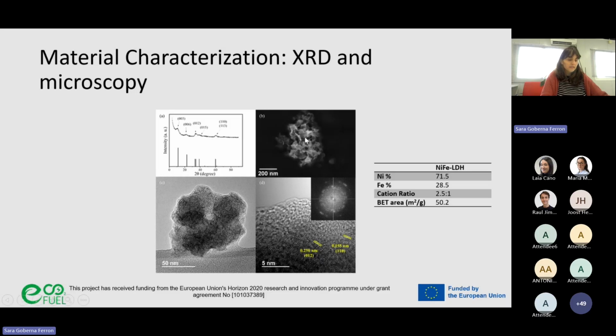Here, the SEM images show that the material is composed of an agglomeration of sheet-like particles, which is the typical morphology of LDH systems. We can observe also that the size of the agglomerate is around 200 nanometers.